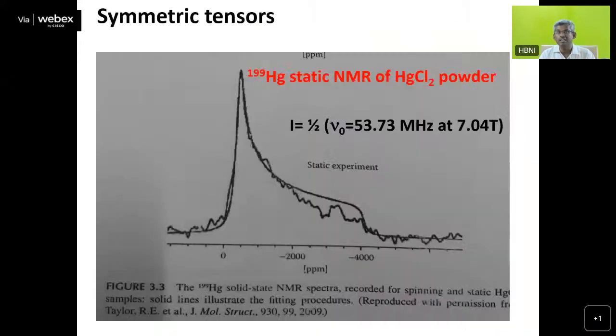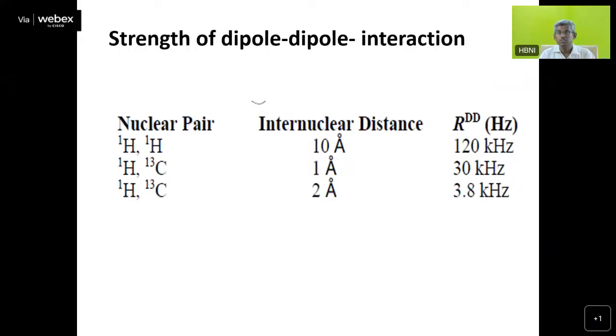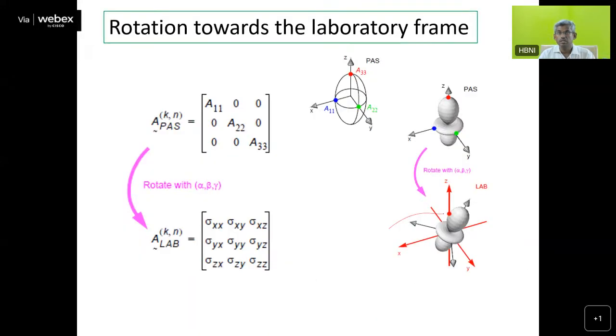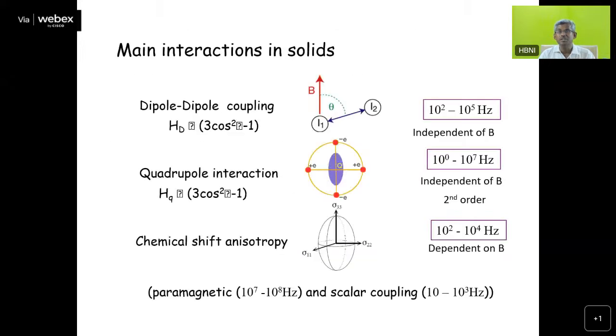For example, a situation like this will come. Let me quickly go through and then tell you. This type of situation will come. You see here this I1, I2. If you rotate it very fast, all the AB bond vectors or BC bond vectors, or all the randomly oriented bond vectors, will align at an angle theta, and now the angle theta is nothing but 54.74 degrees.